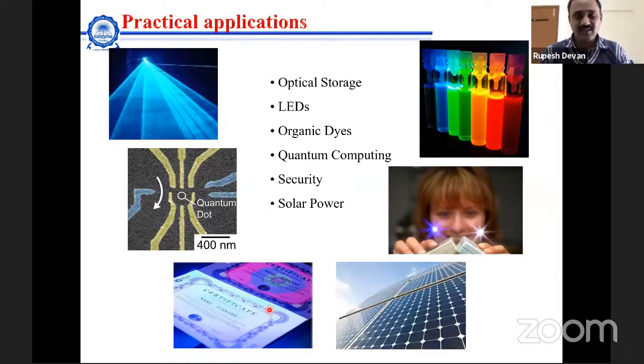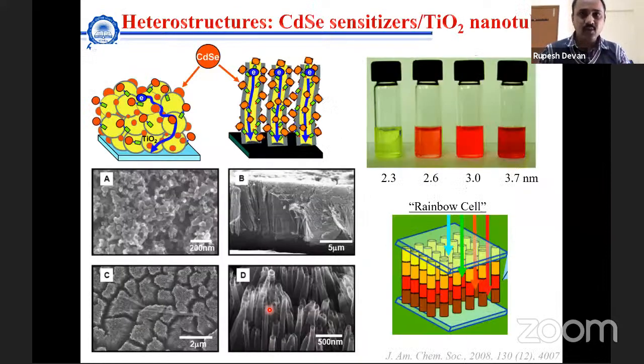Then next comes solar cell, solar power. So quantum silicon is being used. But what excites more is the heterostructures of this quantum dot. If you look at this picture, these are the particles of titanium, and then comes the particle of CdSe. These are closely compacted, even though the surface area is larger. So the path traveled by the electron was taking a longer distance. But if you compare the tubes, which are over here, the tubes have a larger surface area compared to particles, and then they have been attached with the quantum dot. So this created a lot of excitation, and this improved the efficiency of the solar cell as well.